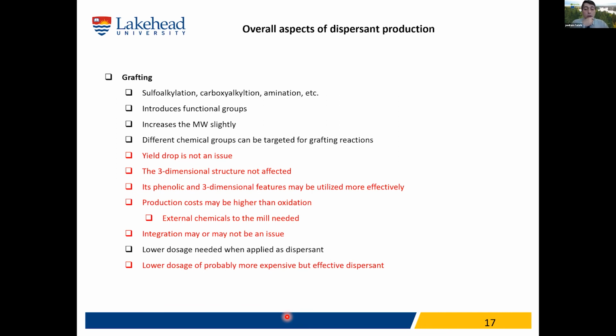The structure of lignin is not affected, and this is very important for dispersant development. So its phenolic group is not much affected. The 3D structure will be there, but production cost, again, depends on the chemical you want to use for your reaction; the production cost may be cheap or may not be cheap. In terms of integration, some of them can be integrated into the kraft pulping process or other pulping processes, but you may need some external chemicals. Because they are more effective, a lower dosage is generally needed than with the oxidized ones. So the compromise is that a lower dosage is needed, but the production cost may be, not all the time, a little bit larger.